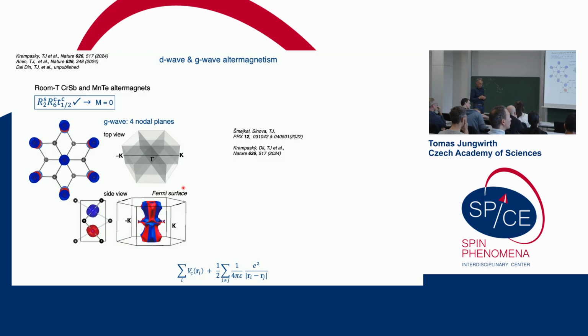So far what I discussed was a D-wave altermagnet. It's called the dice lattice. Dice lattice, okay. So this is a G-wave altermagnet because we have this hexagonal lattice which generates a symmetry which is spin rotation together with a 6-fold real space rotation transformation. As a result, we do not have 2, but we have 4 spin-degenerate nodal surfaces in the momentum space Brillouin zone of the non-relativistic electronic structure. And as a result, you have spin polarization outside these 4 spin-degenerate nodal planes, the strong non-relativistic spin polarization.